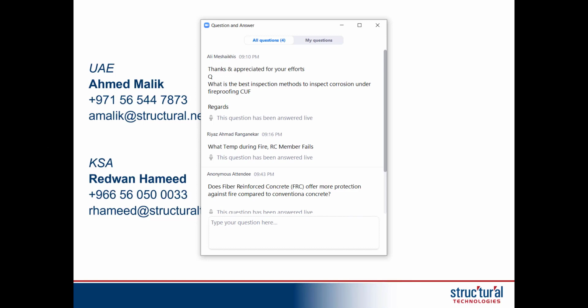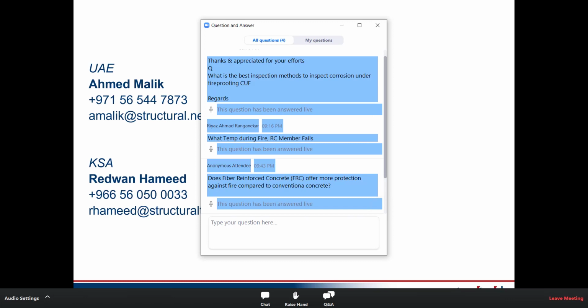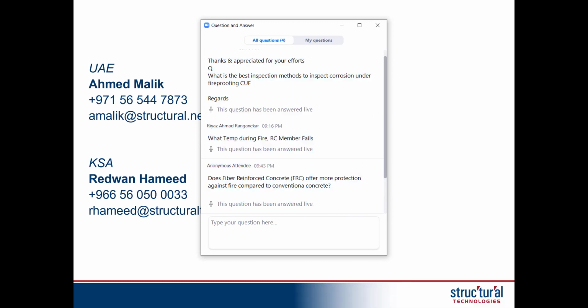All right. Well, another question is, are pre-stressed and post-tension members more vulnerable under fire without any additional fire protection measures? Yes, they're more vulnerable, just as I indicated earlier. So there has to be additional means and methods taken as they are provided in the code, additional concrete cover, and then additional mild reinforcing steel placed within the member to provide protection during a fire event. As I indicated, there's a tendency for relaxation, so they're losing their stress. As we understand, the reason with post-tensioning and pre-stressing is to provide compression on the member so that we can have smaller amounts. We know concrete's very strong in compression, very weak in tension, so we're trying to remove a lot of the tensile forces on the member so it's able to make them thinner and smaller.